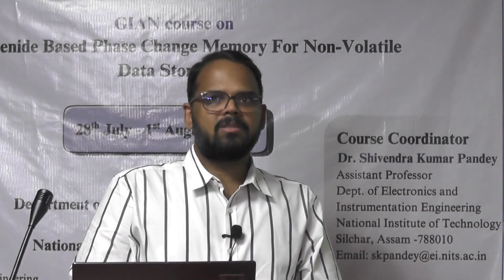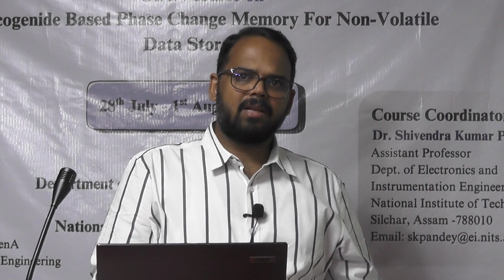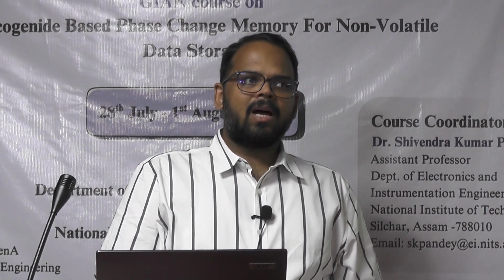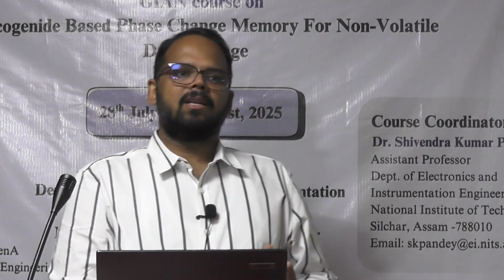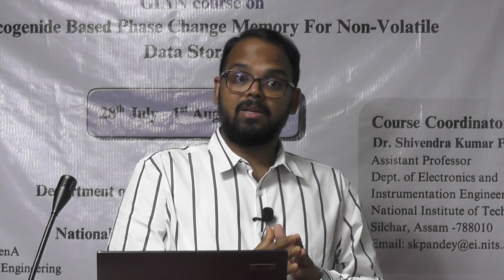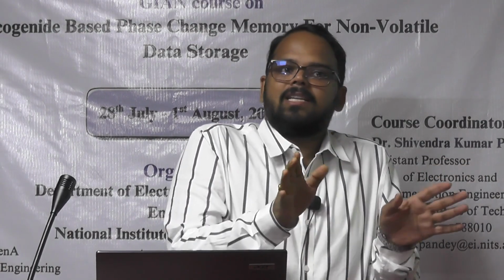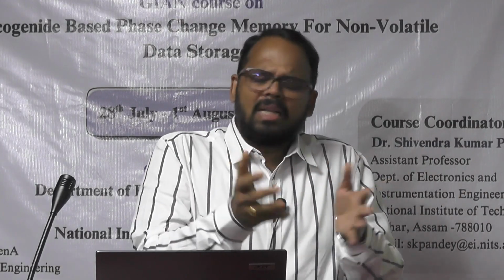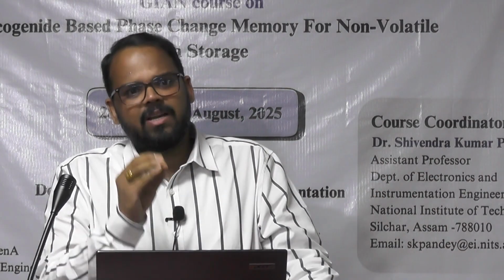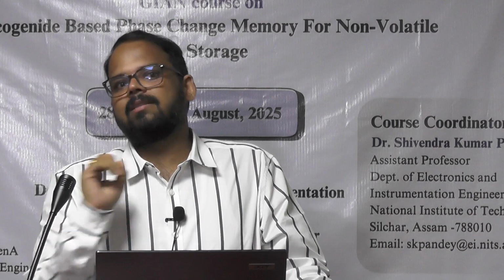If I talk about this material here, the 312 crystal has a stable configuration, and some other like 225. So if you have that desired crystal, and it is getting oriented with respect to temperature, then you will get a stable memory. If I want some particular crystal, and upon increasing temperature that one is going down and another one is increasing, then it is not stable. Some phase segregation is happening. So it is very important what you are targeting. It should be oriented. Then only we can say that yes, this is stable.